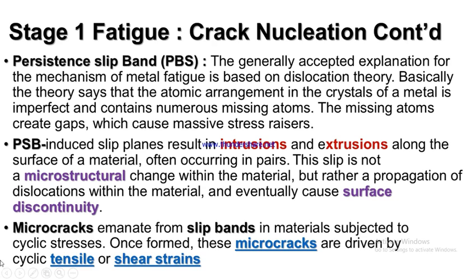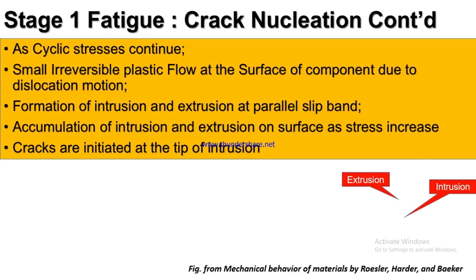This persistent slip band system induces slip planes and results in intrusion and extrusion along the surface of the material. Microcracks begin to emanate from the slip band system, which will lead to crack propagation. Crack propagation will definitely lead to rapid fracture, and then we say that the material has failed under fatigue.